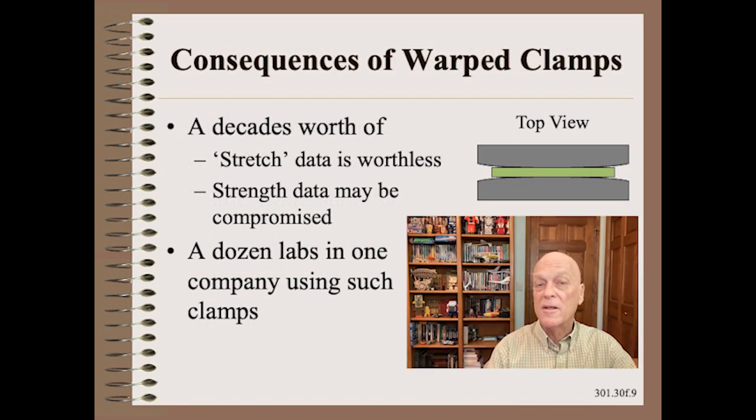The consequences of warped clamps could be quite serious. First, the ultimate strain data, often called stretch, would be essentially worthless if there were slippage. Second, it is possible that the strength data may also be compromised. There were a dozen labs in one large company using just such clamps.